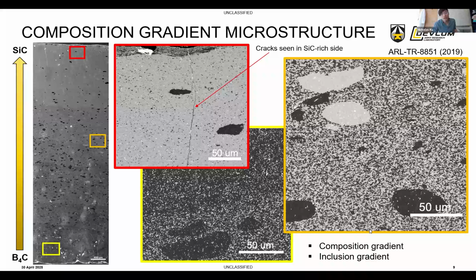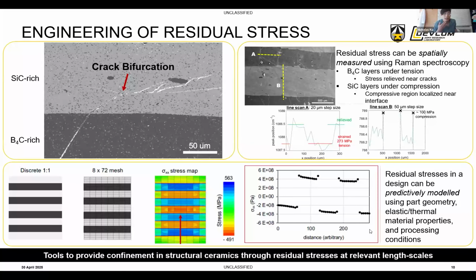So I would say there's a lot of work and design that could be done in order to increase that mixing, whether it's changing the auger design or changing the mixer itself. But we are getting these large clumps of one material in the other, right? That's kind of where we're at right now. And then in terms of the discrete layered materials, residual stress is a big one, right? Whenever you're trying to thermally process two different materials that have different coefficients of thermal expansion, you build up some sort of residual thermal stresses.